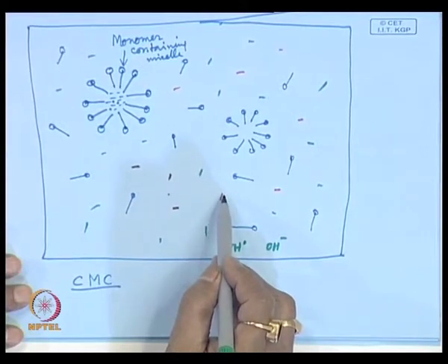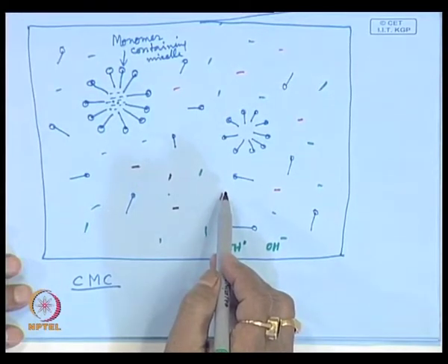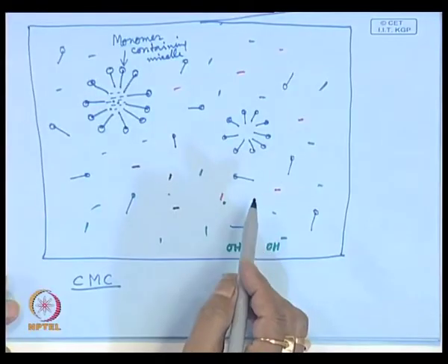Once it initiates the monomer, some polymer is initiated in the aqueous phase. Try to understand: polymerization is initiated in the aqueous phase. Gradually, it will attract more and more monomer, or it will interact with more and more monomer. So, it will continue the propagation step. Through the propagation step, that growing chain radical will grow bigger and bigger. As it grows bigger, what happens? It becomes hydrophobic. Once it becomes hydrophobic, due to growth of this free radical size, it will try to phase out, come out of the aqueous phase. Eventually, soap molecules are there like friends, they will cover it.